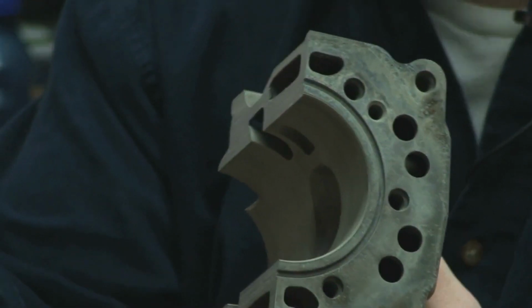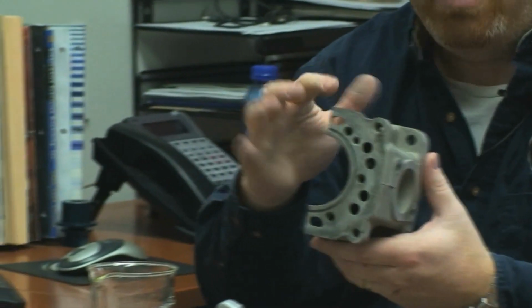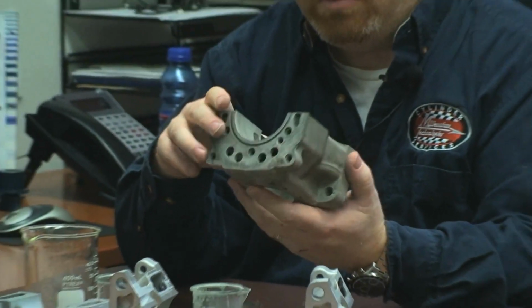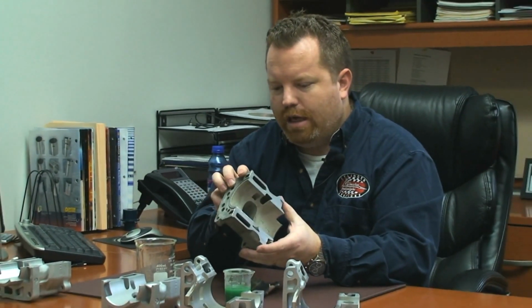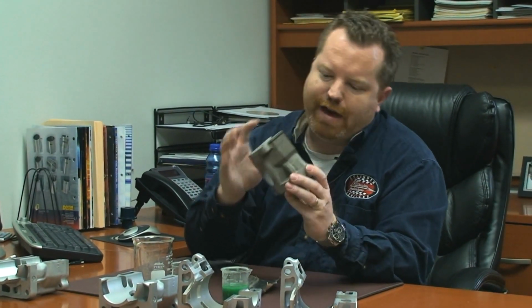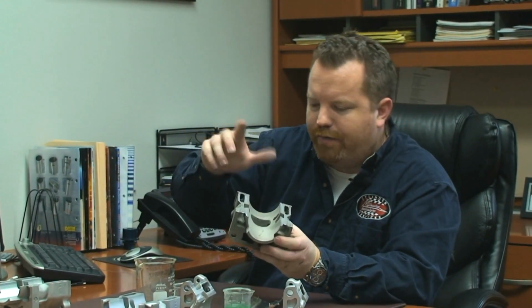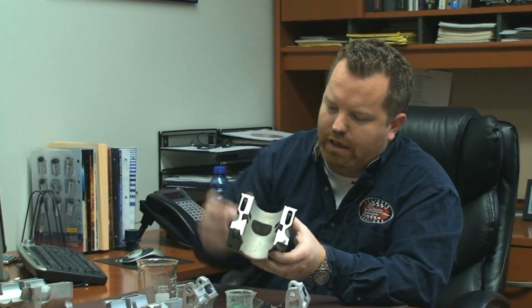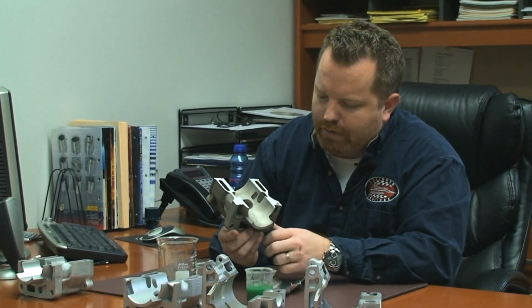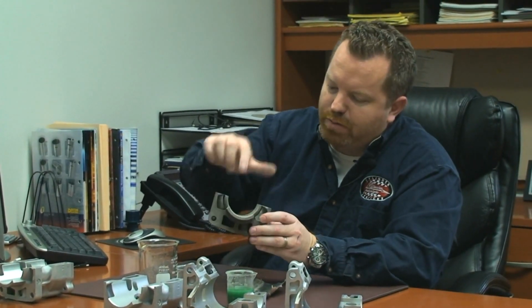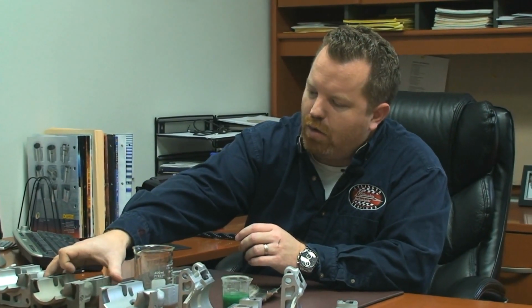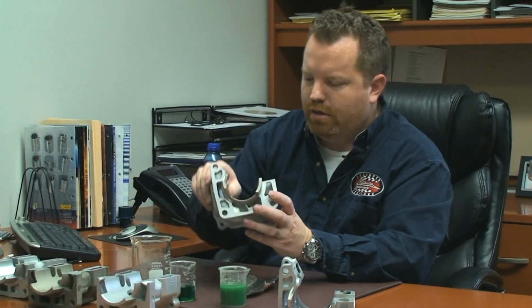and when you're done, it looks like this. As you can see, the difference in the color of the aluminum. This is clean aluminum. It gets quite a smut buildup on it, so we have to do some cleaning processes to make it look better and to have the cylinder look real nice. After this, it goes through the cleaning processes. We get a buildup a lot on 2-strokes, but on 4-strokes, it's usually on the bottom, and we clean everything up and chamfer all these ports and the bottom on a 4-stroke cylinder so that when we hone it, it won't catch and chip and do a bunch of bad things.